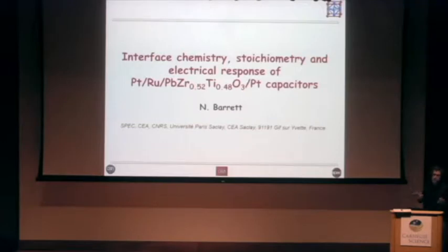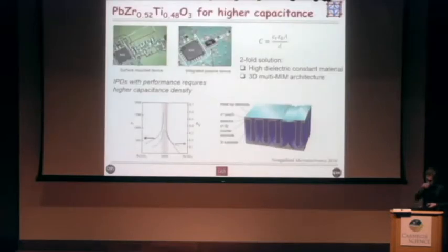Here, we sacrificed the spatial resolution, and instead, thanks to tuning the photon energy that we're going to be using to carry out electron spectroscopy, we're obtaining depth resolution. And this allows us to look at surfaces, and it will allow us to look also at interfaces buried several tens of nanometers beneath the surface. So the object, the material in question, is PZT. It's a morphotropic phase boundary.